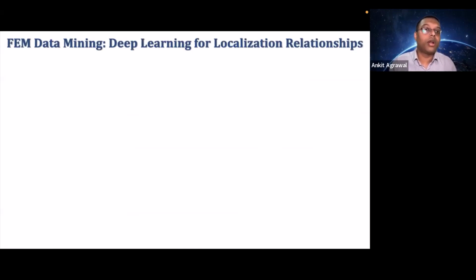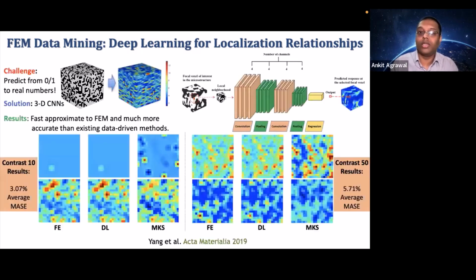Another example is from the finite element modeling domain. I'm sure you know finite element simulations are very powerful for doing homogenization and localization models. So here the problem is that if you have a two-phase composite, and you apply a loading condition on top of it, how does that get distributed at the micro scale? That is in a sense the localization problem. It's very challenging, because from just two-phase or 0-1, we need to go to real numbers. We tried a lot of different models for this problem, and we found that a special way to apply 2D CNNs or extending it to 3D CNNs works quite well.